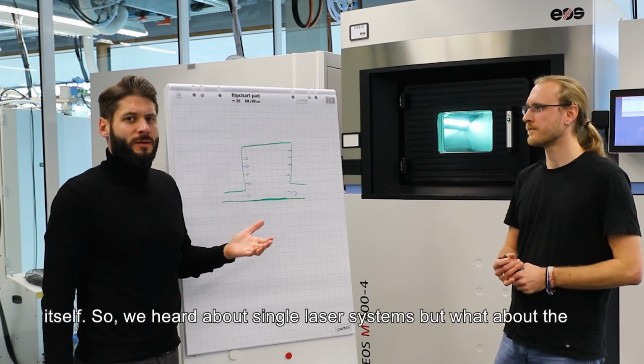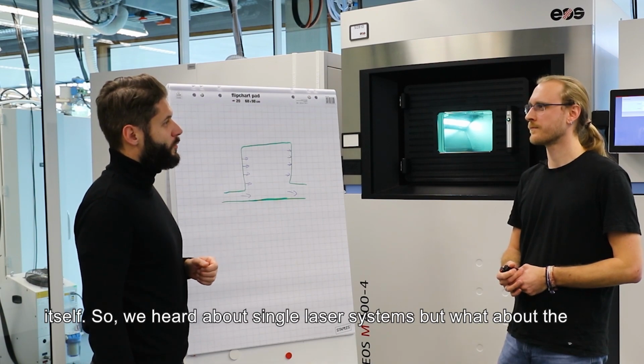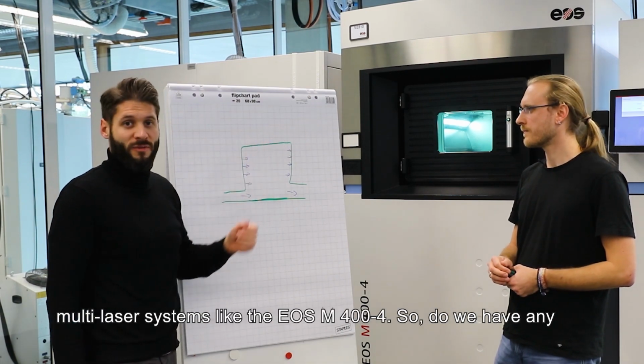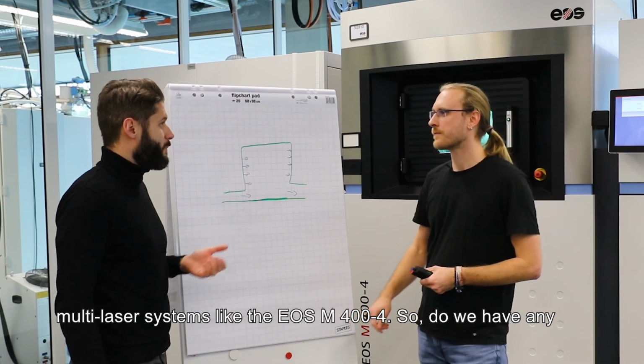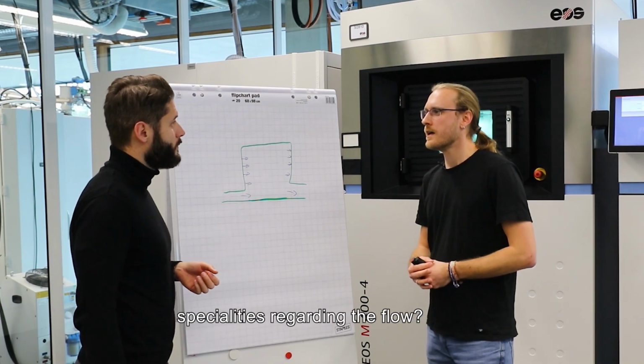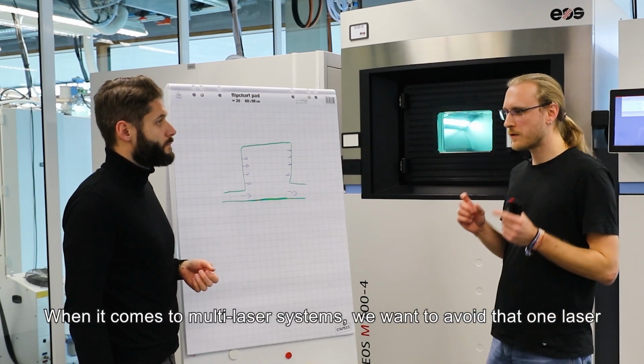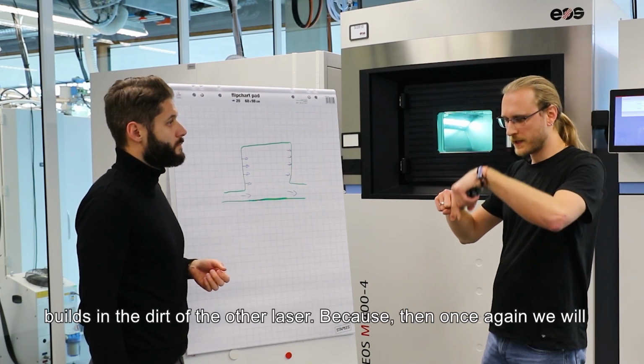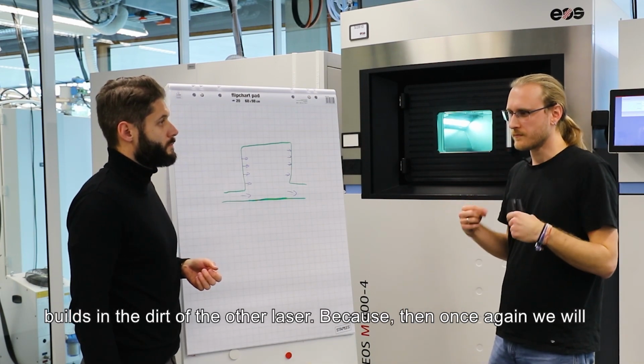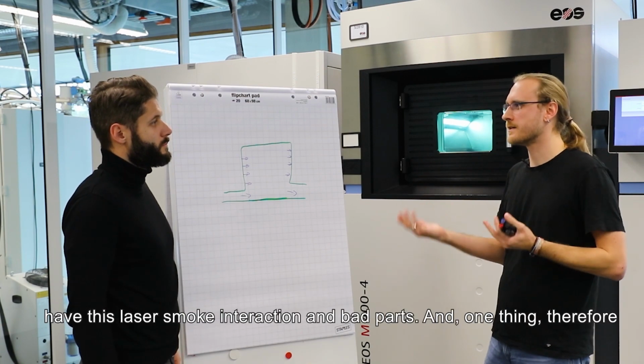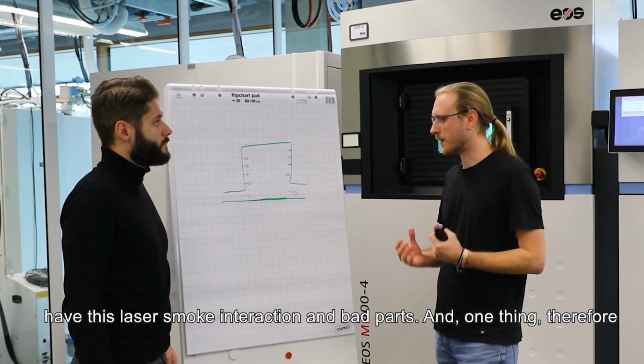So we heard about single laser systems, but what about multi-laser systems like the M400-4? Do we have any specialties in regard to the flow? Yeah, when it comes to multi-laser systems, we really want to avoid that one laser builds in the dirt of the other laser. Because then once again we will have this laser smoke interaction and bad parts.